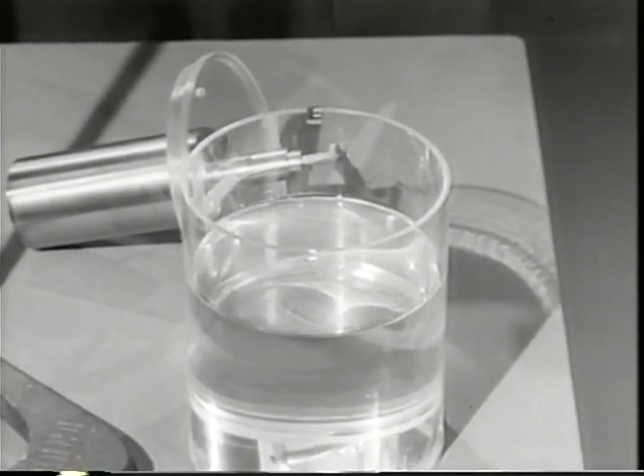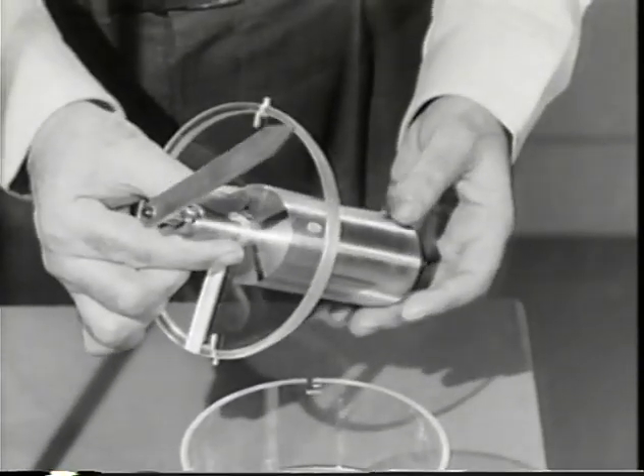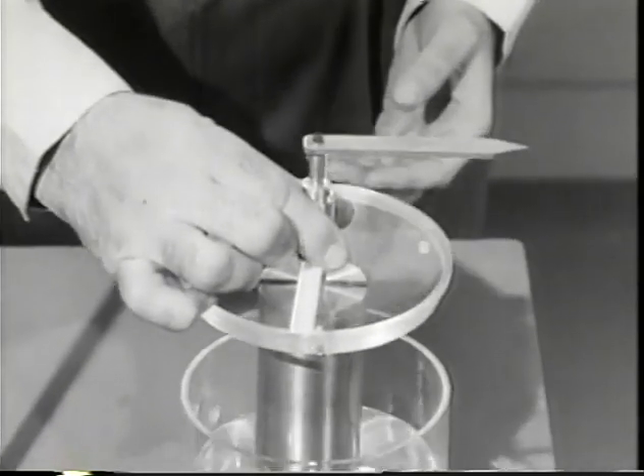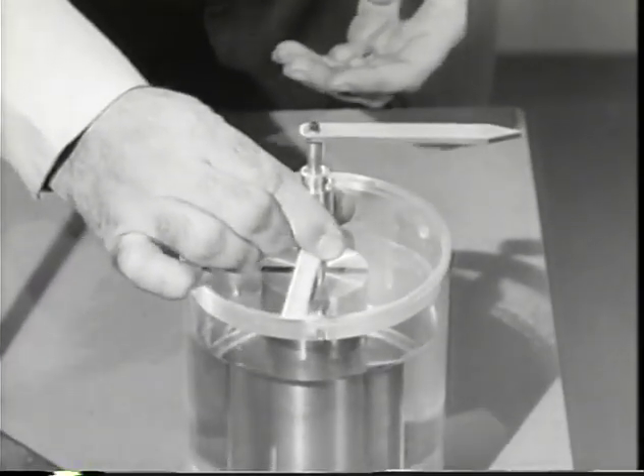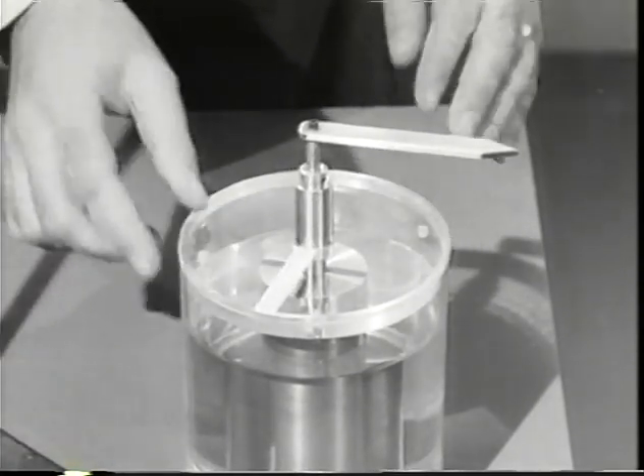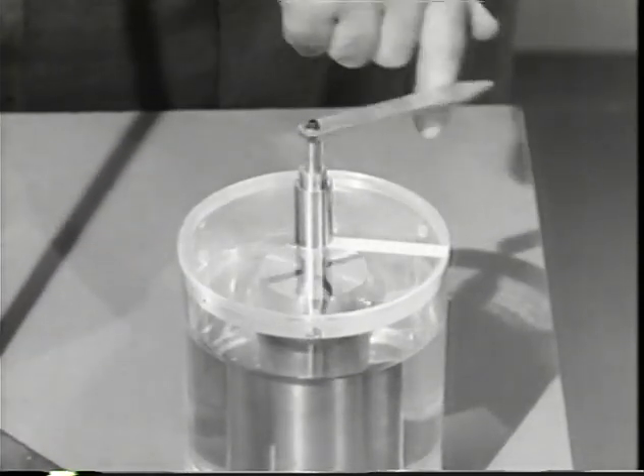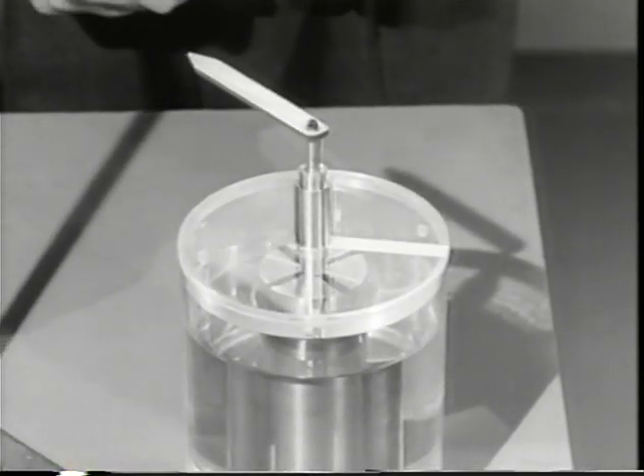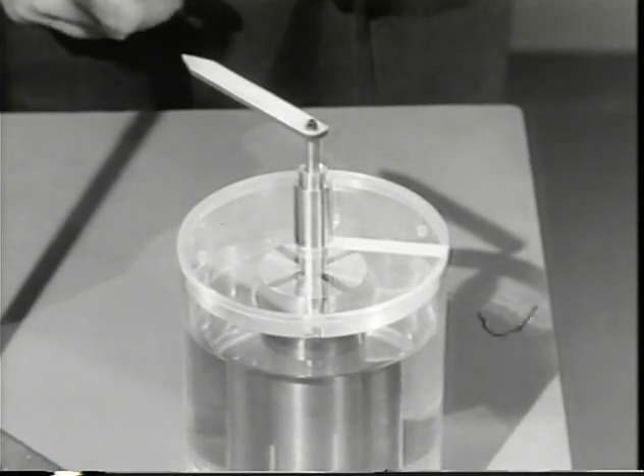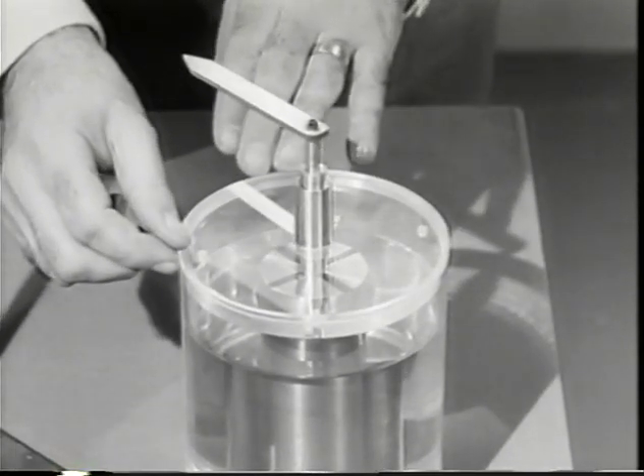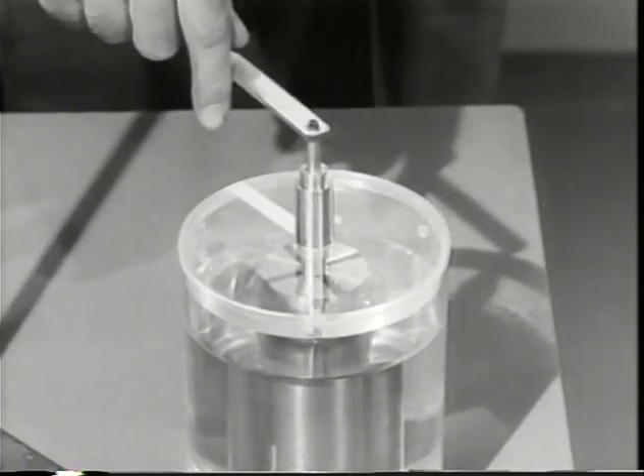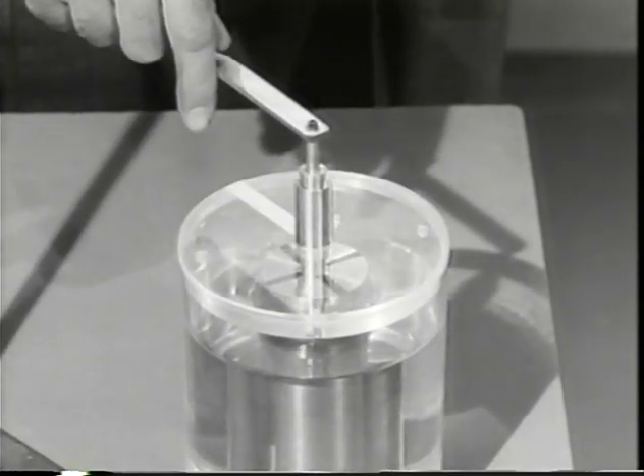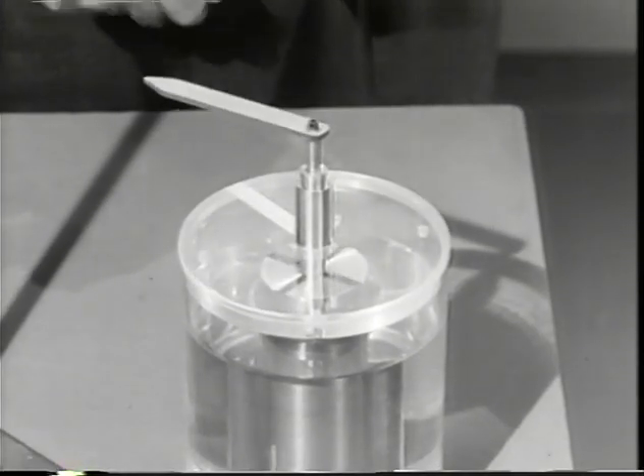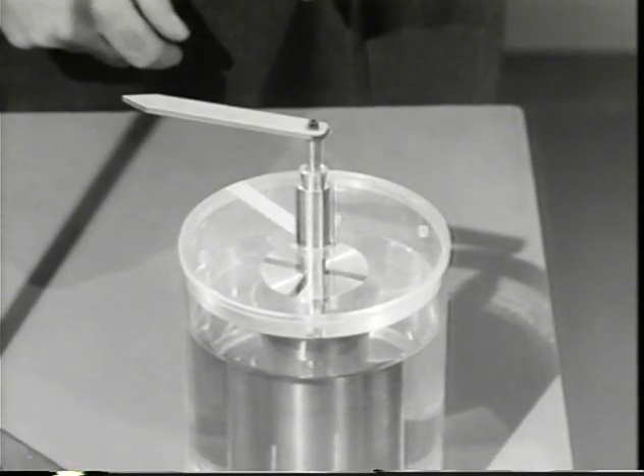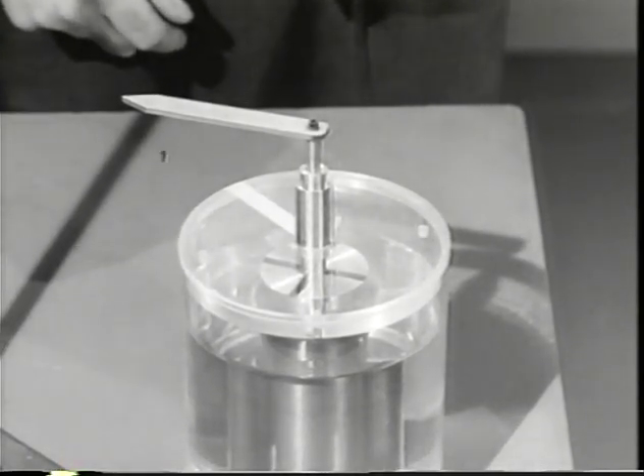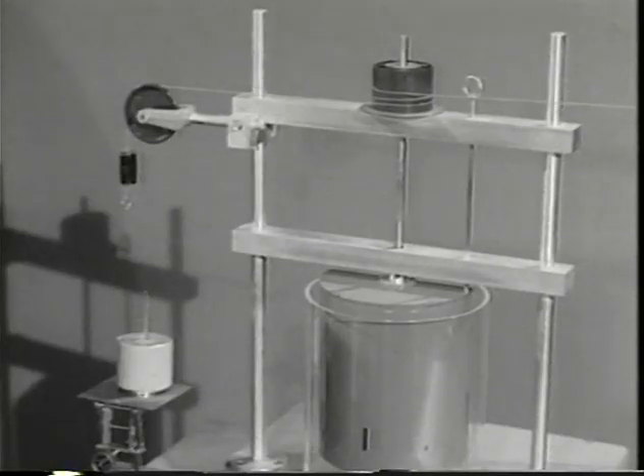Here's some more polymer solution. I can put this cylinder into it, and turn it a full 360 degrees. When I let go quickly, it returns almost half the distance. This time, I'll hold it for a few seconds. Since the fluid has a fading memory, when I do let go, the recovery is a much smaller fraction of the original deformation. We can make quantitative measurements of viscoelastic behavior in this type of apparatus.